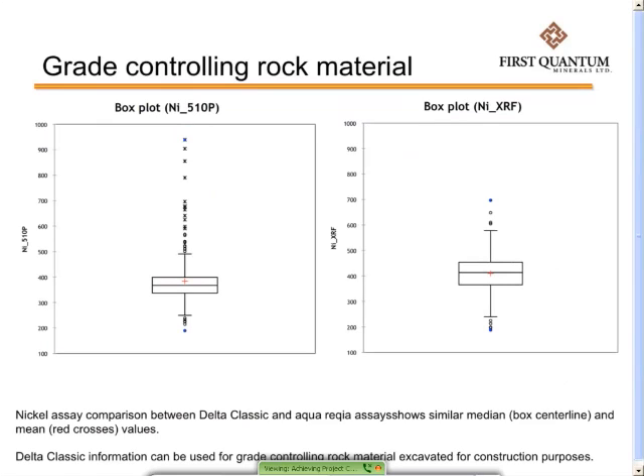Checks were carried out to understand the behaviour of the instrument on these rough, unprepared samples when compared with the laboratory assays of the same material. Here, a similar mean and median was found, the XRF reporting slightly above 400 parts per million nickel, where the laboratory showed just below 400 parts per million.